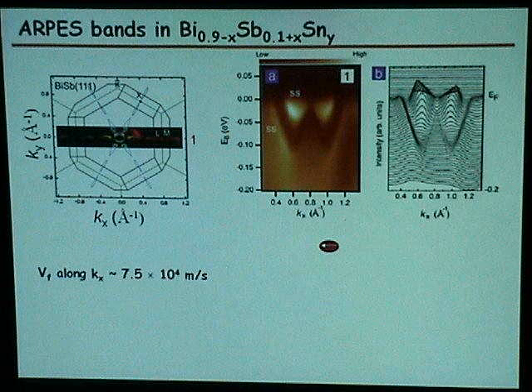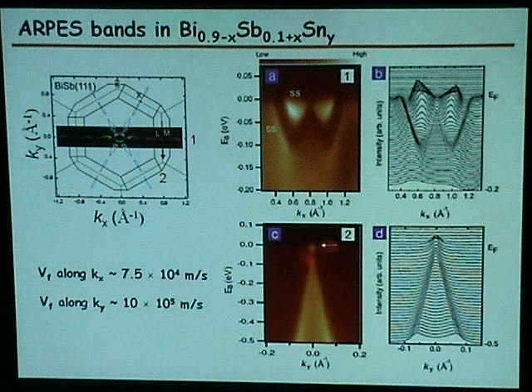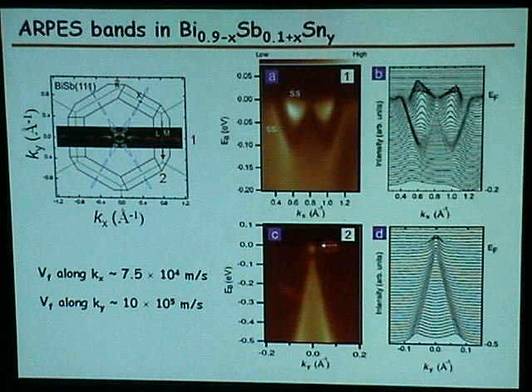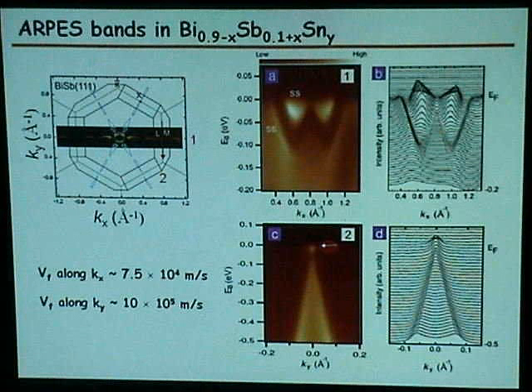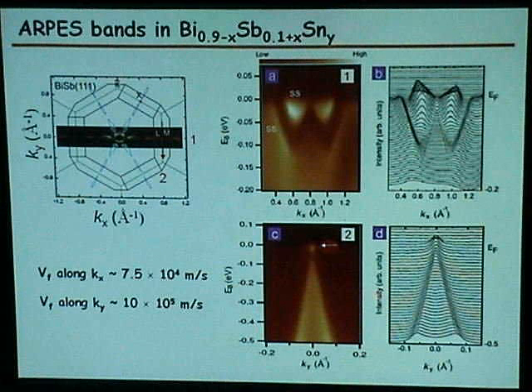Okay, so if I take a cut perpendicular to it, then what do I see? If I go through this, I see some intensity here, then very much linear bands. And the Fermi velocities are so large, and remarkably, they're almost the same as graphene. This Fermi velocity is just the same as graphene. If I take a graphene spectral function and compare it here, it will look like electron-doped graphene.